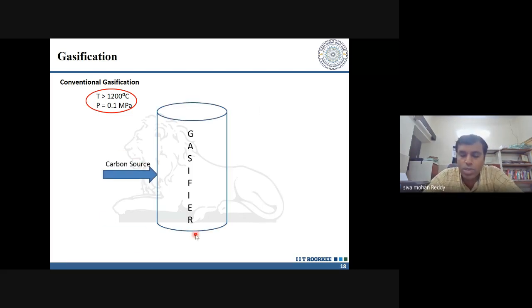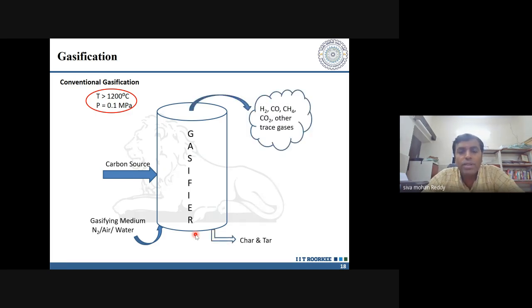If you feed a carbon source to a gasifier, typically at greater than 1200 degrees centigrade at near atmospheric pressure, maybe 1 to 5 bar, in a nitrogen, air, or water system, that will result in hydrogen, CO, methane, carbon dioxide, and other hydrocarbons being generated. Along with that, you have char and tar being formed. Now, the typical operating conditions of supercritical gasification are around 400 to 700 degrees centigrade, and the pressure is around 23 to 30 megapascal, that is nothing but 230 to 300 atmospheres typically.